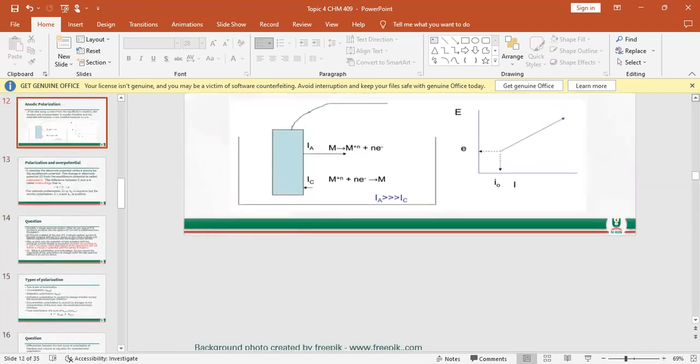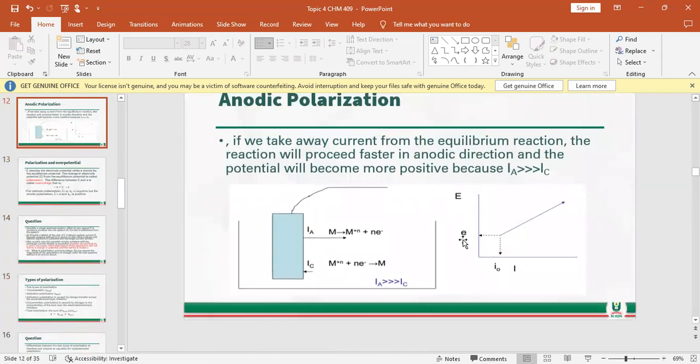So this is for the anodic reaction. E is in each case the equilibrium potential. If you trace that graph to this point and drop backward, that gives you the i0, the exchange current density. You can get that from that graph, from that point.